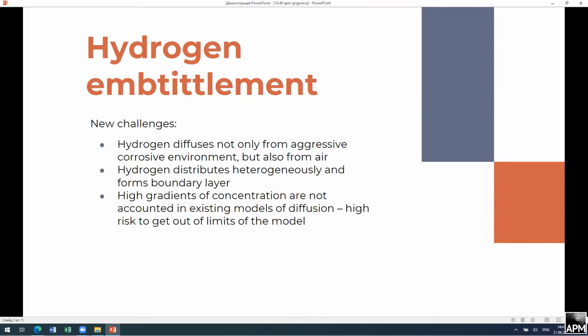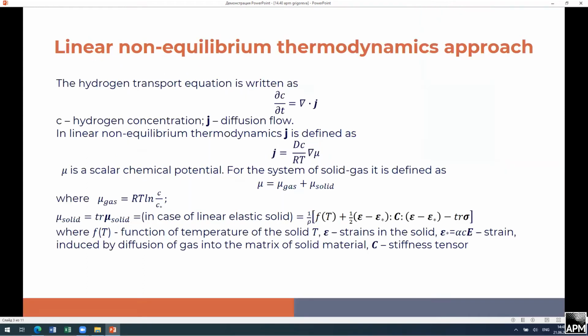So the hydrogen also distributes non-uniformly and forms a boundary layer. And also we experimentally see high gradients of concentrations, which are not counted in existing models of diffusion, because sometimes the assumption of the diffusion model is that the gradients of concentrations are relatively small. Furthermore, we want to take into account the impact of the stress-strain state of the metal and of the induced stresses and strains.